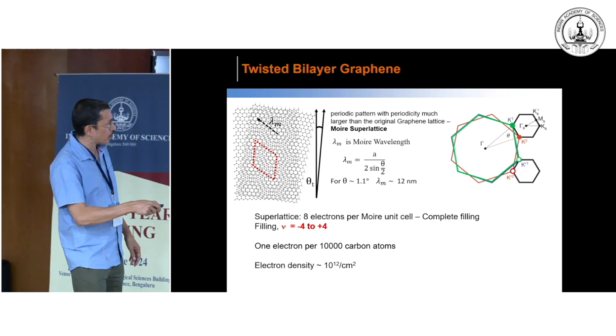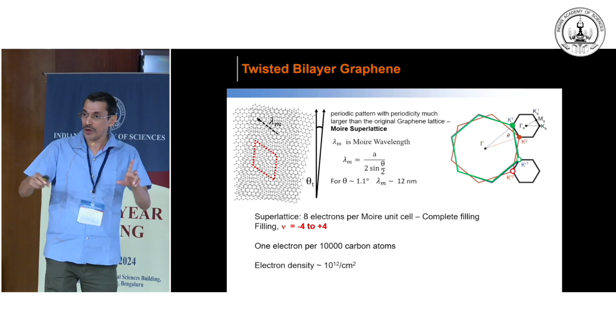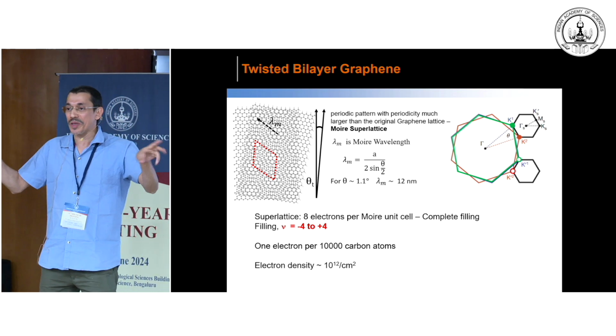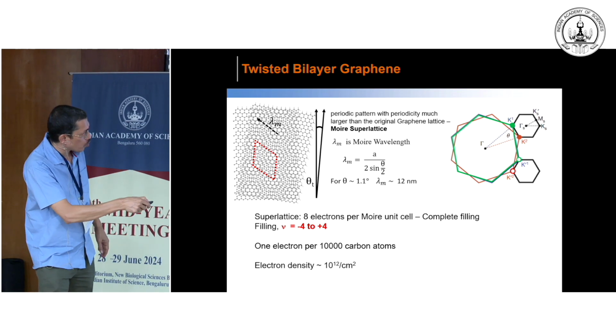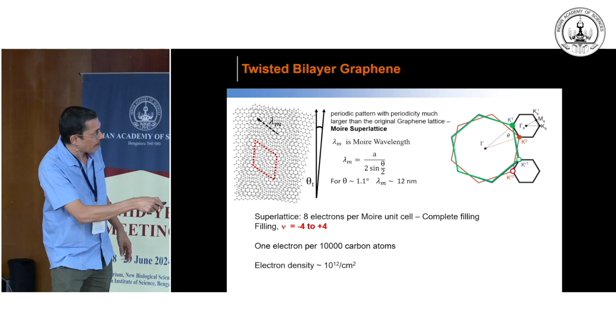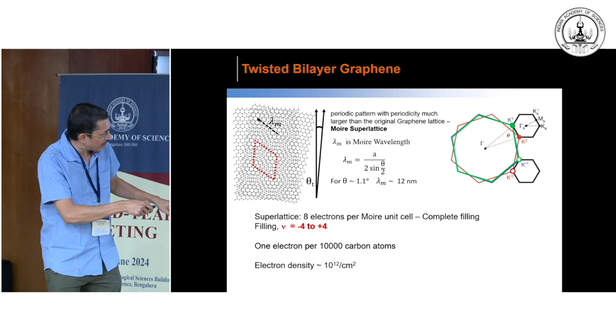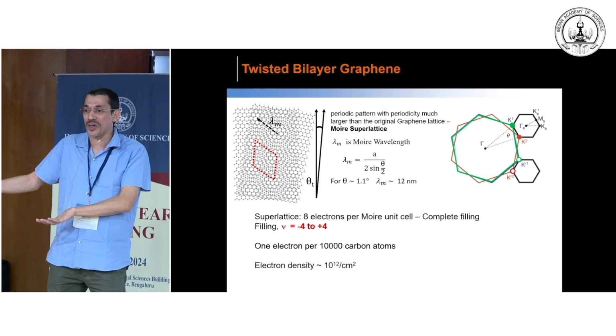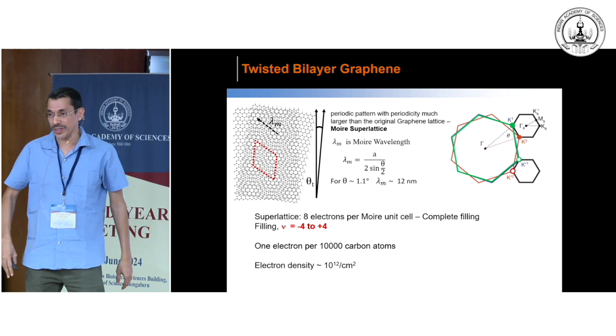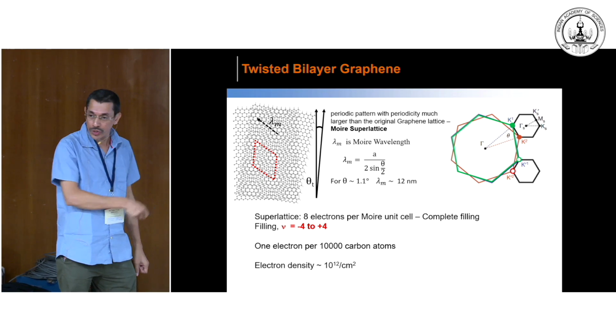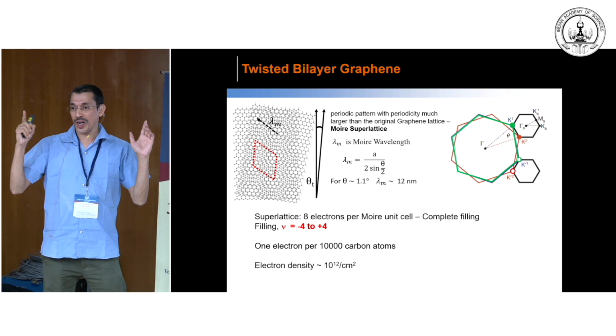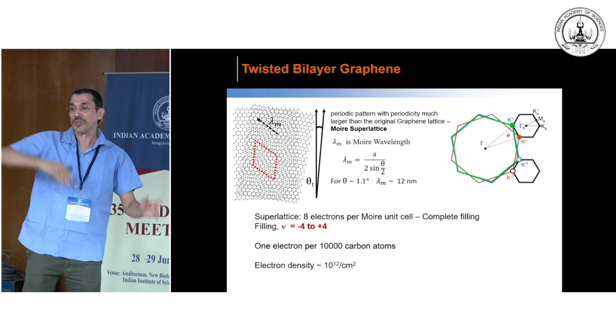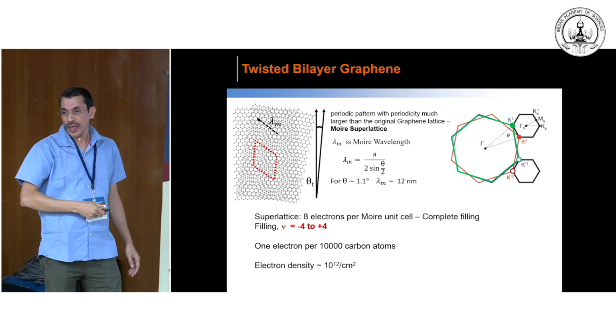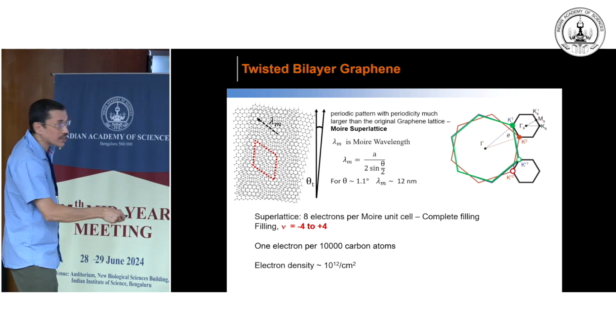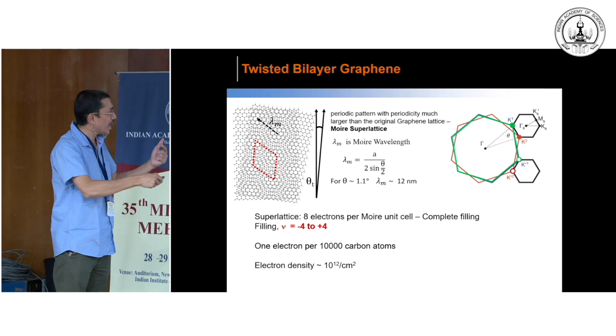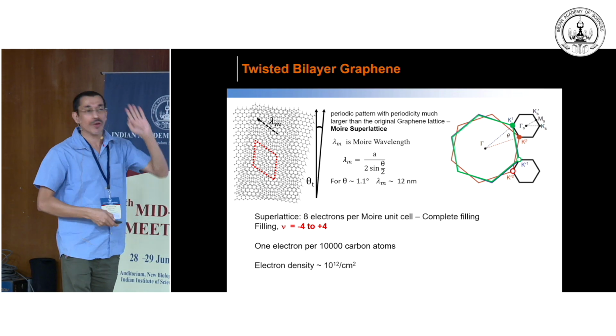yes, the 4 comes because in original graphene there is already 4 degeneracy, because you have 2 spin and 2 valley. But here you can see there are 2 kinds of mini Brillouin zone. One is coming from the K prime of the top and bottom layer, the other is coming from the K valley of the top and bottom layer. So the layer degree of freedom is also important, because of the 2 layers. So that is the reason you can show that this is actually 8 electrons total required to fill or empty, from -4 to +4. So remember, this is the filling I will be talking about, because when I say filling, I will be talking about how many carriers per Moire unit cell.